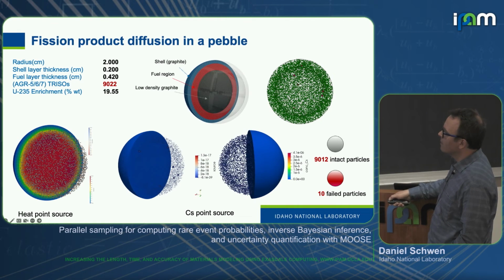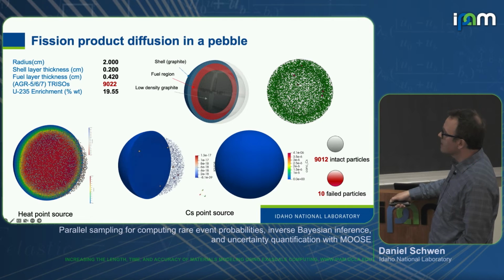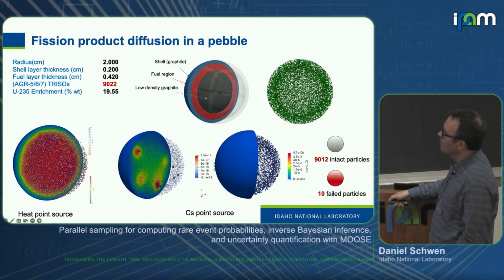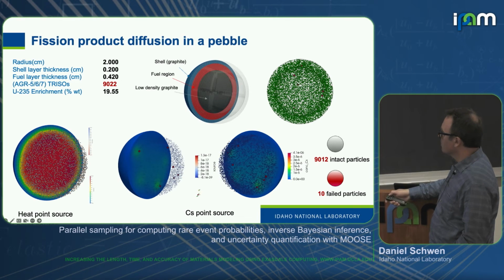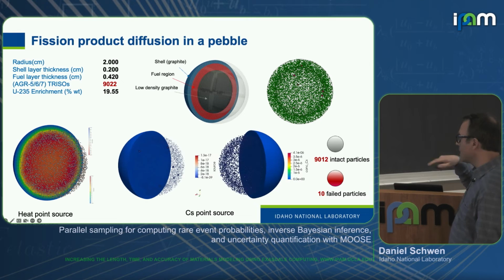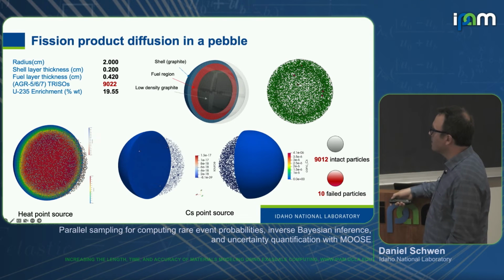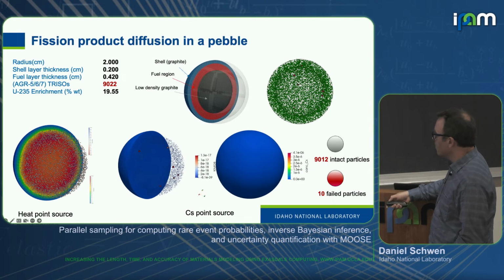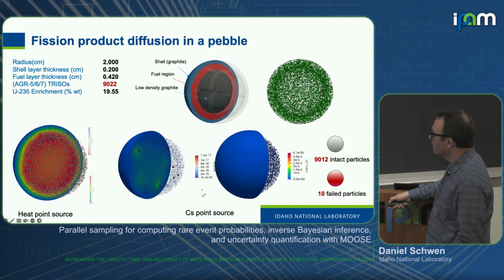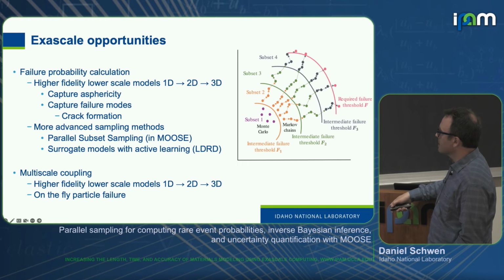So in addition to calculating the temperature by taking every particle as a little heat source, we can also take it as a cesium source, which is the most problematic element that we can have diffusing out, and then we can calculate the cesium transport for this particle. This doesn't yet do the failure analysis on the fly, but nowadays this would be a possibility as well. And then you get the two-way coupling with the temperature distribution from the larger length scale simulation.